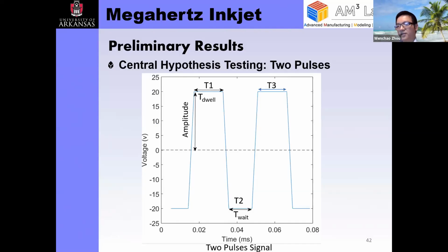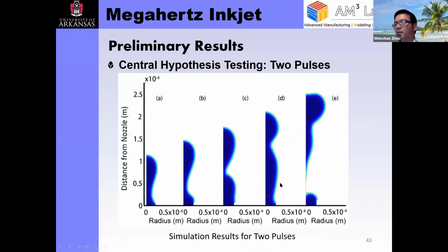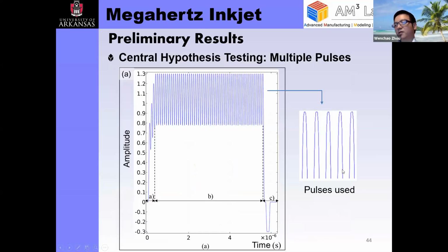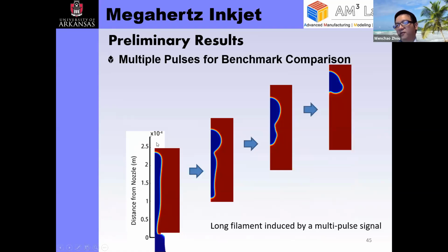So we use this validated numerical model to study two pulses, to see if we can generate a larger droplet size with two pulses at a similar or faster frequency. This is a simulation that we did. After the first pulse, that already pushes half a droplet out, and it's starting to pinch off. Before it completely pinches off, we send a second signal to drive more liquid out, such that these two can merge together to form a larger droplet. We took this idea to an extreme. Instead of just two pulses, we include as many as 40 pulses here, to see if we can get an even larger droplet with smaller nozzles. In this simulation, we form a very long filament, and it breaks off nicely to form a large droplet with multi-pulse.